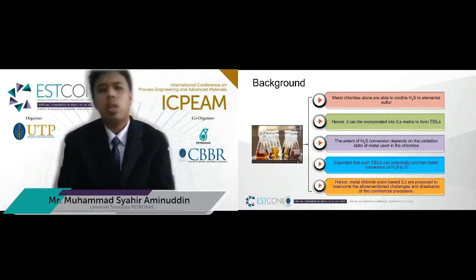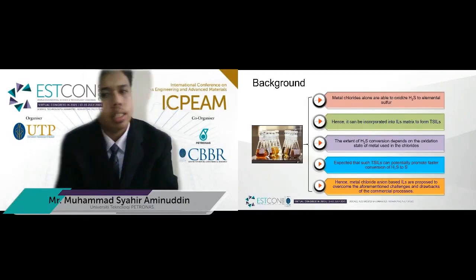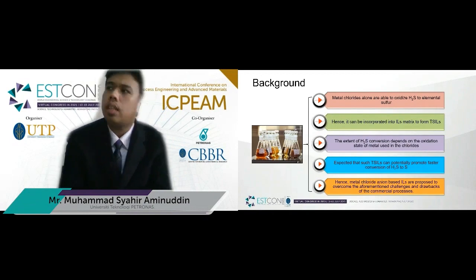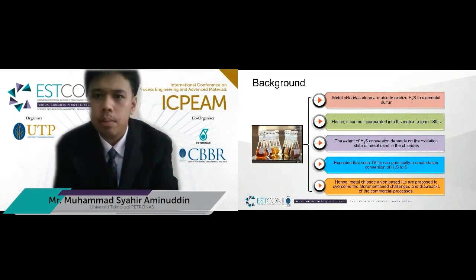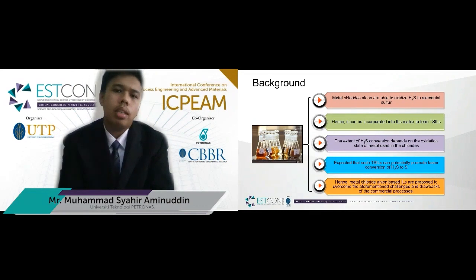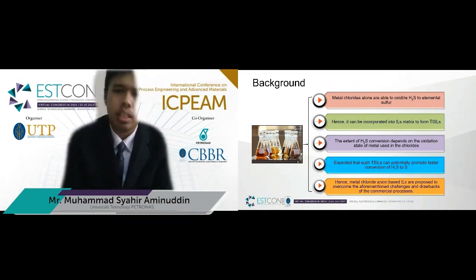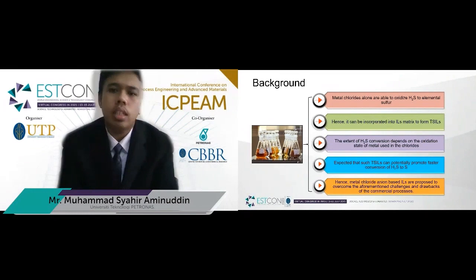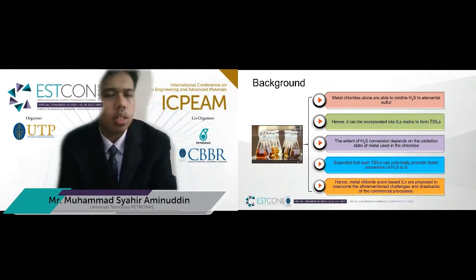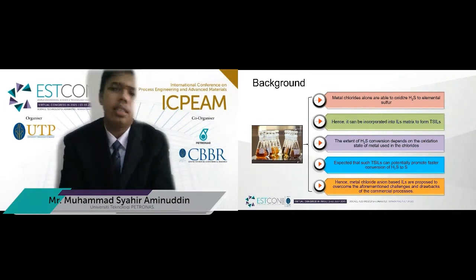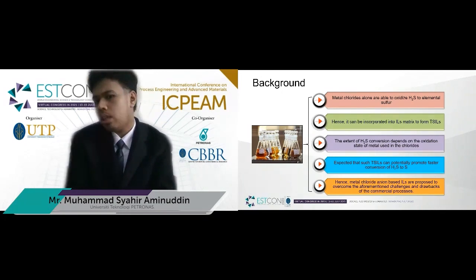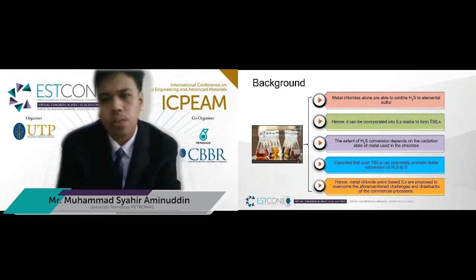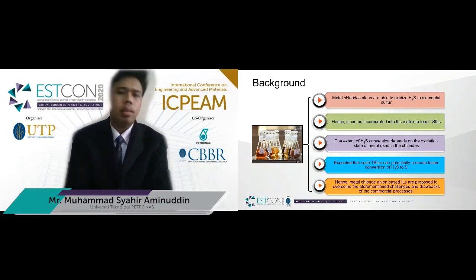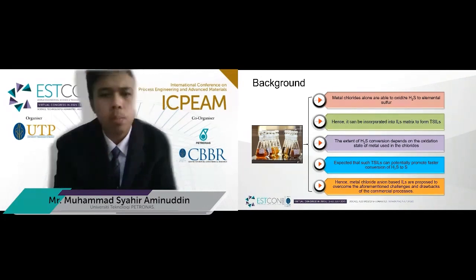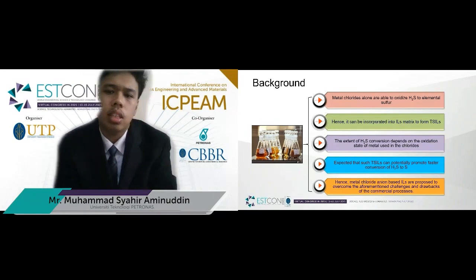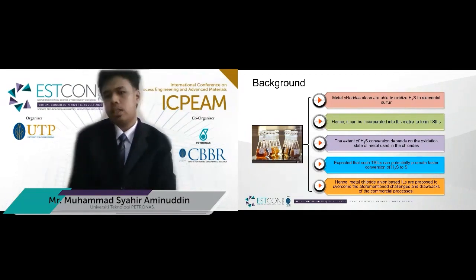That is the reason why we are using metal chloride anion-based ionic liquids. This is because metal chlorides alone are able to oxidize hydrogen sulfide to elemental sulfur. Hence, they can be incorporated into the ILs matrix to form TSILs. The extent of H2S conversion depends on the oxidation state of the metal used in the chlorides, and it is expected that such TSILs can potentially promote faster conversion of hydrogen sulfide to sulfur. Hence, metal chloride anion-based ionic liquids are proposed to overcome the challenges and drawbacks of the commercial processes.